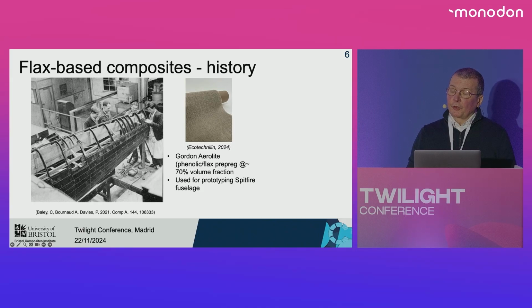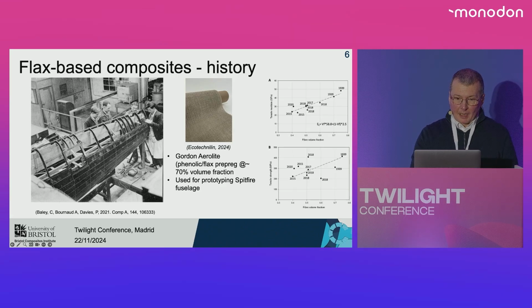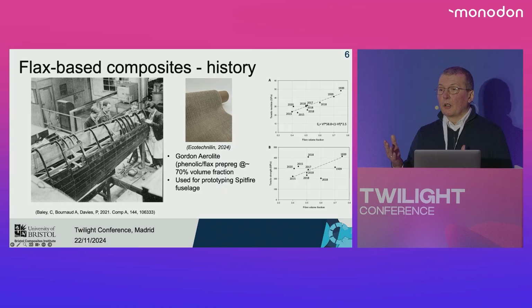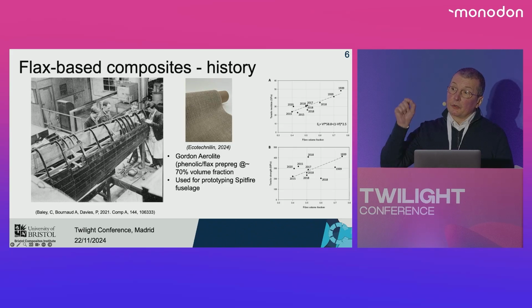Composite that was also quite interestingly insensitive to relative humidity. At the moment, Gordon Aerolite is still the stiffest composite with natural fibers on the market, well, for what is available on the market. And in terms of stiffness, in terms of really tensile strength, only recently some epoxy flax prepregs with 50% volume fraction reinforcement have managed really to reach the tensile strength of the material.